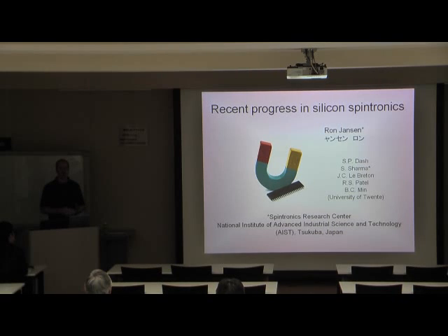It's a low mass material. Also, the crystal has inversion symmetry, which removes one of the main spin relaxation mechanisms like the Elliott-Yafet. And also most of the silicon isotopes don't have nuclear spin, so also spin relaxation via nuclear hyperfine interactions is relatively weak.